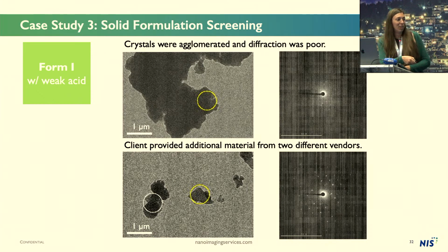So in here, we found a handful of these thin plates that were isolated from the other particles. We were able to get some reasonable diffraction and actually solve this structure. But yeah, it was interesting for us to see that of these 2 different CROs, only one of them could get a good enough sample for this. So this was just a very hard project all around.